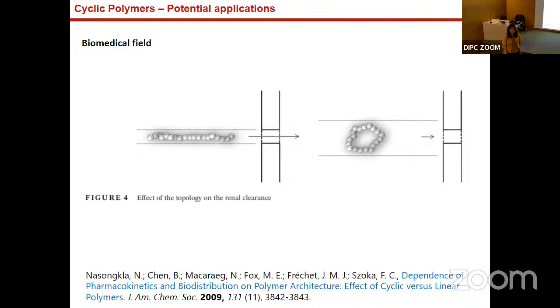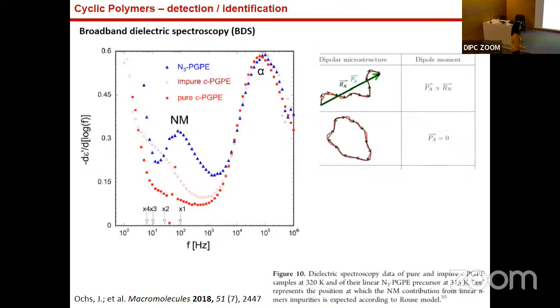I have a curiosity about broadband dielectric spectroscopy and the comparison between linear and cyclic. If you can show the graph, the alpha relaxation is shifted to lower frequency because the Tg is higher, also in the calorimetric results. But I wonder if there are other secondary relaxations like beta, gamma, and if there are some differences. Yes, the beta relaxation also shows some differences.